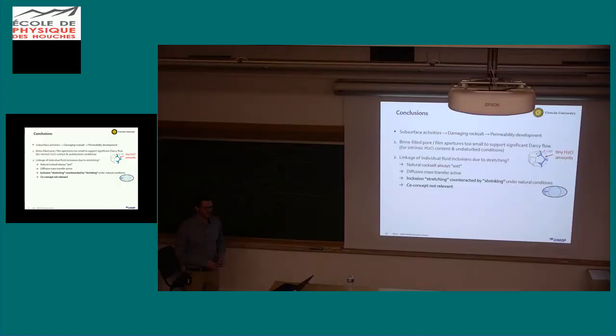Of course, when we have subsurface activities, drilling, formation of caverns, we damage rock salt. This can lead to increased permeabilities in the damage zone around wells. But looking at undisturbed conditions, we figured out that the water content that is there and the geometry of the pore structure is too small to support significant Darcy flow.